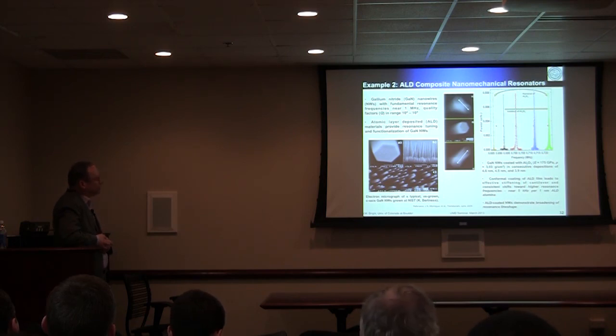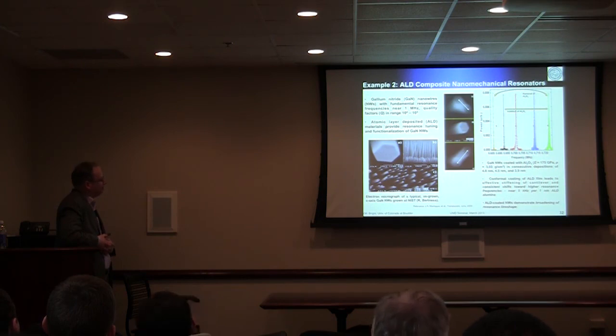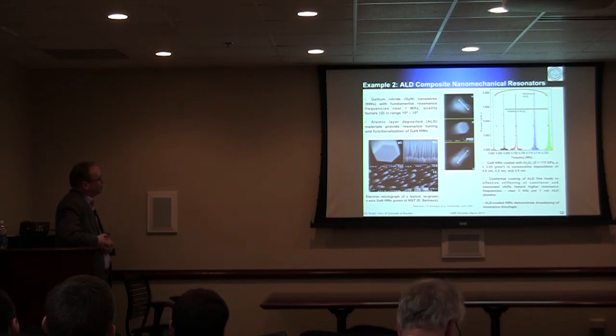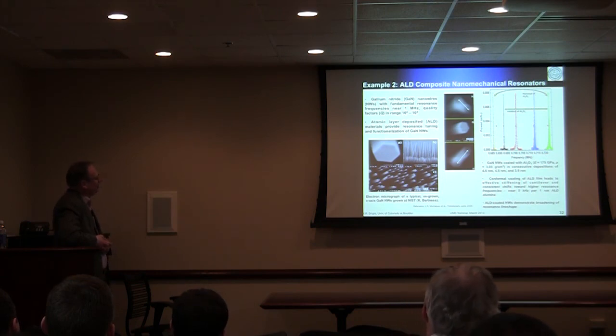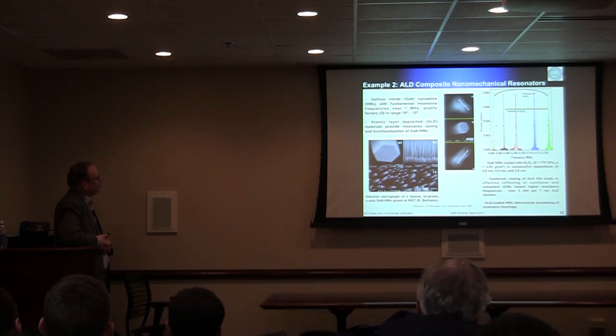100,000 is not that unusual for this type of device. This is a single crystal gallium nitride. The nice thing about this process is they're grown by MBE, so they are defect-free. They're C-axis, so they're pretty high quality to begin with. The other nice thing about gallium nitride is it really doesn't oxidize and doesn't contaminate. So you can really make very nice devices with this type of nanowires.